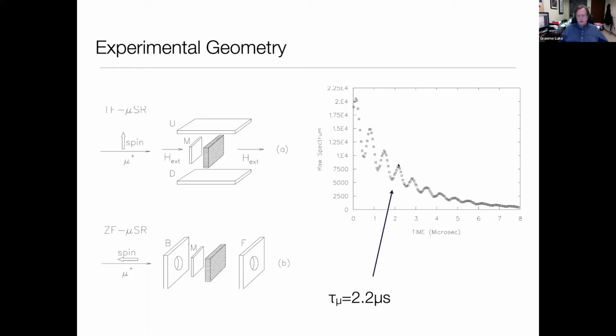So here's an actual decay curve. This is just showing muons that have been implanted probably into a piece of copper or something like that, with about a 60 Gauss magnetic field applied to it. And on top of the muon decay curve, you see an oscillation of the polarization as the muons' spins precess, pointing either towards the detector when they decay or away from the detector when they decay.